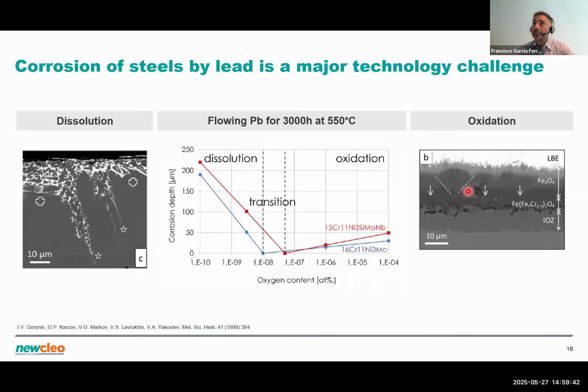Now, coming to arguably the most important technological issue for lead fast reactors, we have corrosion. This is a challenge because steel behaves in lead the same as sugar would behave in water, roughly. I'm being very bold with this statement. It's not really the case. But the corrosion can be very aggressive depending on the conditions you're looking at and the steel and so on. So it's a complex problem. Corrosion can proceed either by dissolution, for example, as we see on the picture on the left, if the oxygen content in the liquid metal is very low. So for a given duration and temperature, low oxygen could lead to this kind of situation. And for high oxygen content, corrosion could take the form of oxidation.